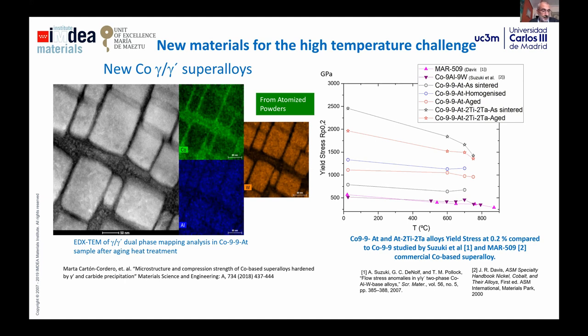and the punches. But also, powder metallurgy offers a lot of opportunities in the development of new materials. Because the way in which we produce the alloys allows us to do things that are not possible to do in alternative technologies. In this case, this is the microstructure of the new cobalt gamma prime superalloy, in which we can reproduce the conventional nickel-based superalloy microstructures. And in this case, through powder metallurgy, we can reach much better properties than using alternative technologies. This new superalloy was developed in 2004, 2005, and in the last years we have been working through powder metallurgy in order to improve this alloy.